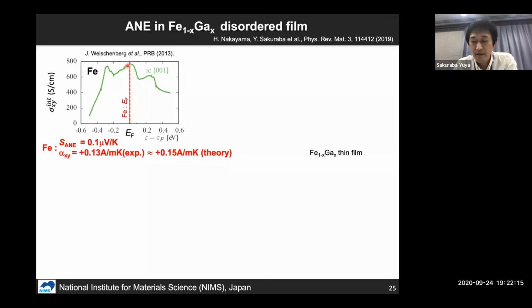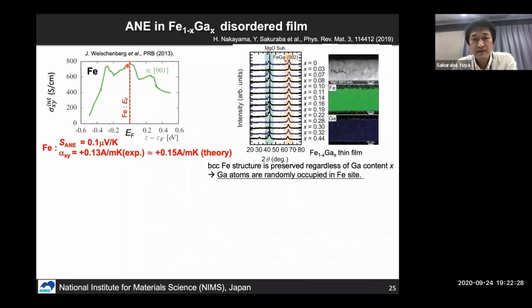So we considered whether or not we can enhance the anomalous Nernst output in pure iron by adding other elements. So in our recent study, we tried to substitute iron with gallium. We made iron gallium epitaxial thin films using a co-deposition technique with an iron target and an iron gallium target.